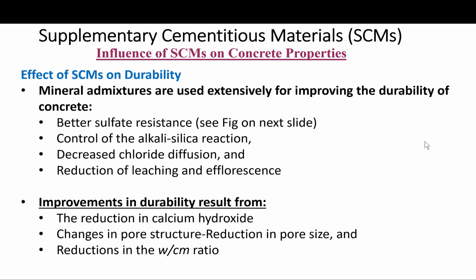Mineral admixtures also reduce the expansion due to alkali-silica or alkali-aggregate reactions, a subject that will be discussed later in durability. The relative abilities of different admixtures almost parallel their influence on sulfate expansion, which is primarily due to the reduction of the alkali content of the cementitious blend and the reduction in the pH of the pore solution, because we took calcium hydroxide out.